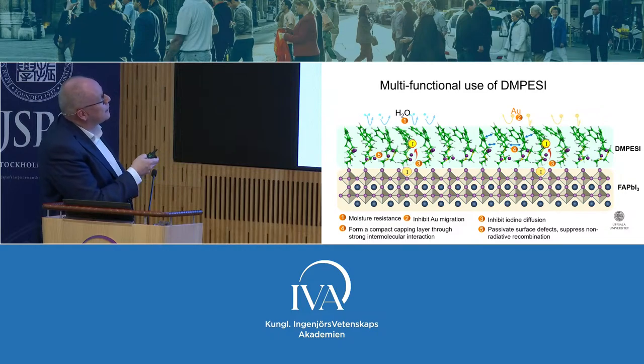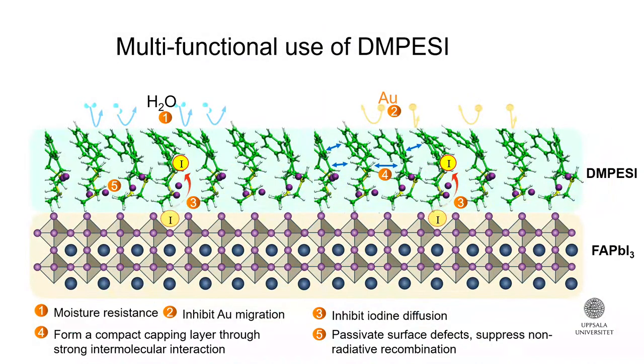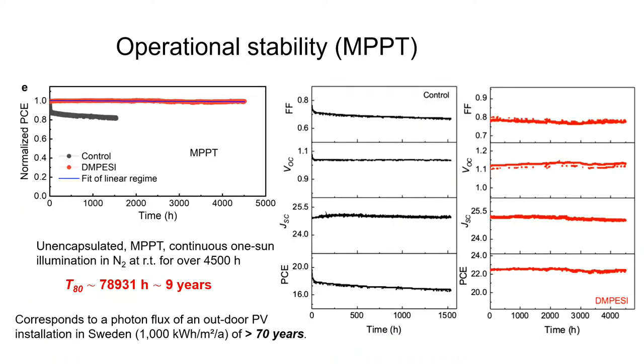things you can do. This layer with the sulfonium blocks the surface, so we avoid penetration of water, so it stands humidity. You avoid diffusion out of iodine from the perovskite layer, so you block that, that's a problem. You avoid metallic contact diffusion, so it's a very solid layer on the surface, and then you also passivate sites which lead to recombination. So with these materials, we have achieved an excellent stability.